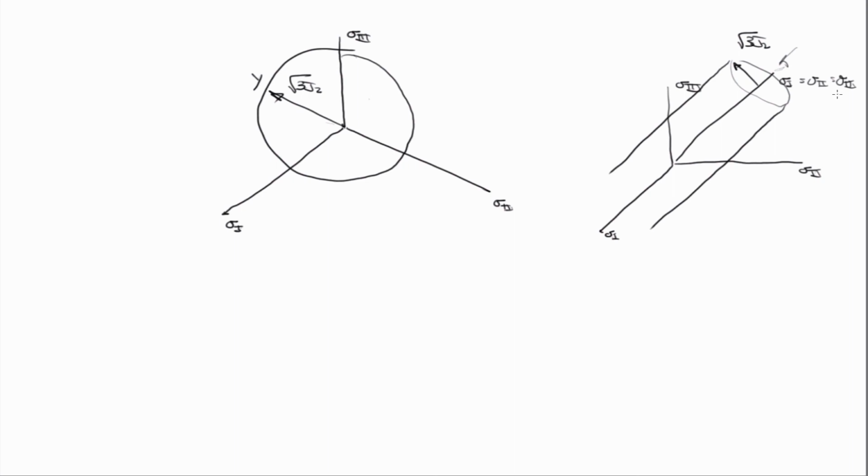So the idea is, you test to see if you're elastic or plastic. If you're elastic, you just apply Hooke's law and go to the next step. If you're plastic, you have to do something special. The way you test is usually you take what's called a trial step. You take a load step as if it's purely elastic. Then you compute the yield function and find out, am I inside or am I outside? If I'm inside, it's just elastic.